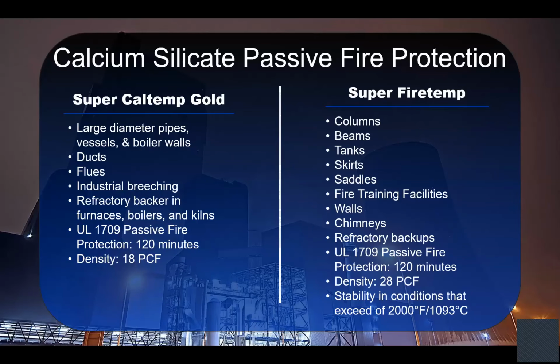Primary applications for both materials, the Super CalTemp and the Fire Temp, provide a 2-hour rating for UL 1709 as passive fire protection. For those of you who aren't familiar with 1709, that is a hydrocarbon pool fire where the temperature, because it's hydrocarbon in this test, goes from 0 to 2000 degrees in 5 minutes. And the insulation has to perform for 2 hours or 120 minutes. These are primary applications for both of these boards, the Super CalTemp Gold and the Super Fire Temp products.